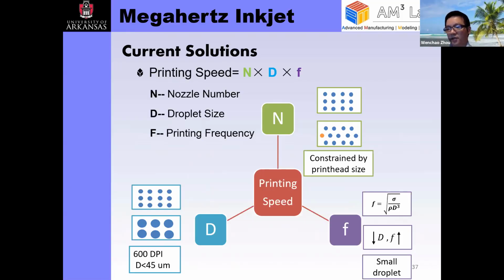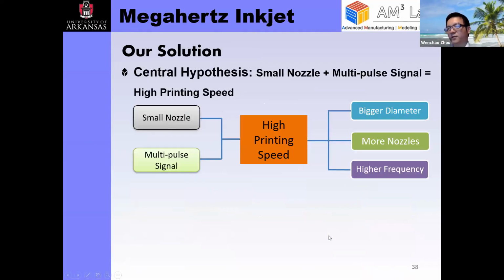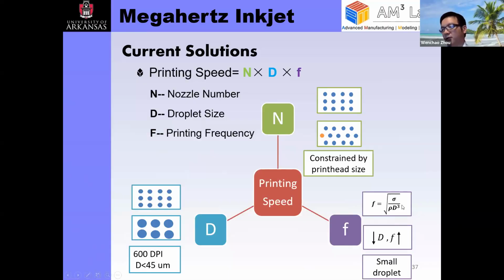You can't get much higher, not even to mention order of magnitude difference. So that puts a limit on it. So our goal is to see if there's a way that we can surpass this limit. One of the things that we realize in this equation is that this d here is actually more related to the nozzle diameter instead of the droplet diameter. Although in modern inkjet printers, the nozzle diameter is typically similar to the droplet diameter.